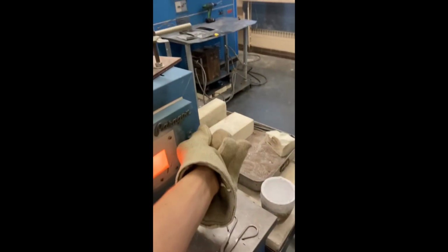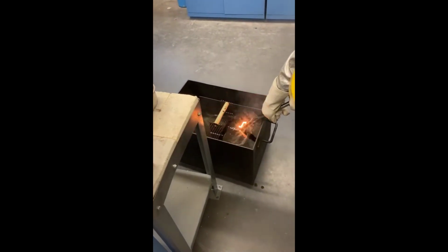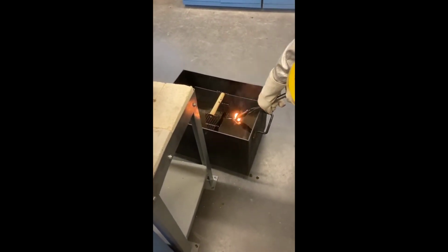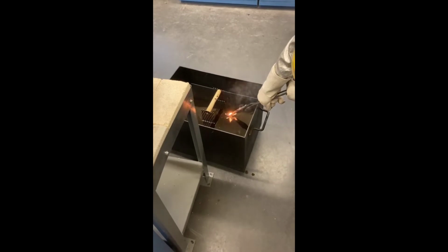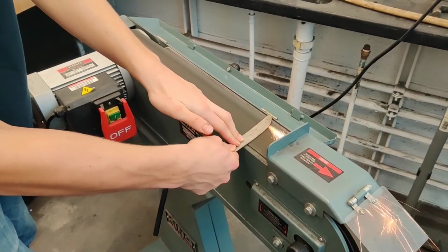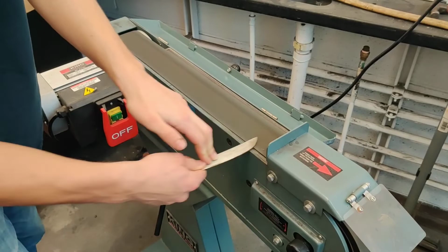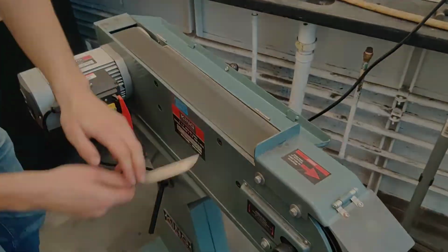Team members wearing full protective equipment removed the blade from a box furnace once it was held at 900 C for 5 minutes in order to quench it. This quench was done in oil so as to lower the heat transfer rate and minimize quench cracks. This process also introduced some oxides on the surface and means the blade is once again ground. Once that was done, the blade should have increased hardness, and this was confirmed with a Rockwell hardness test.